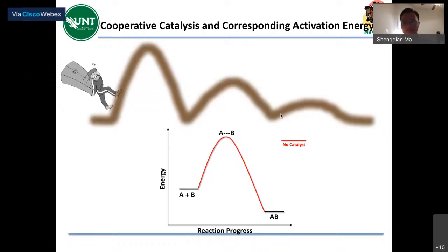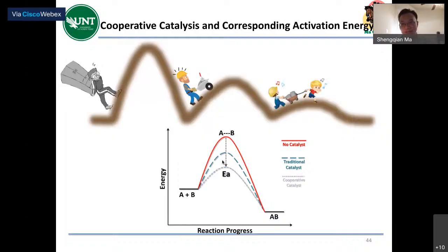When we're talking about catalysis, right, essential is to reduce the activation energy barrier, to speed up the reaction. So it's with the catalyst, the activation energy barrier. Thermodynamically, a lot of reactions are favorable, right? But kinetically, we need to reduce the activation energy barrier. So for traditional catalysts, like zeolite and the metal oxide, they can do this, but need relatively high temperature and high pressure, right? So enzyme, as I said, they're perfect, very sophisticated. They can do these kinds of reactions at a very mild condition, right? So reduce this activation energy to a very low level. That's why they can catalyze these kinds of reactions at ambient temperature, ambient pressure.